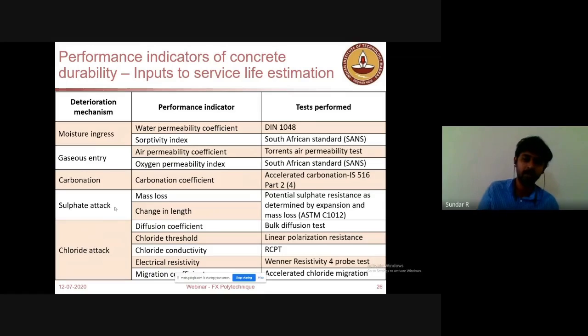So similarly for chloride attack, we have numerous tests which could be useful, like diffusion coefficient, which is basically the natural ingress of chloride into the concrete based on concentration variations, and chloride threshold, which is the minimum amount of chloride required for initiation of corrosion. I will explain these a little bit in later slides.